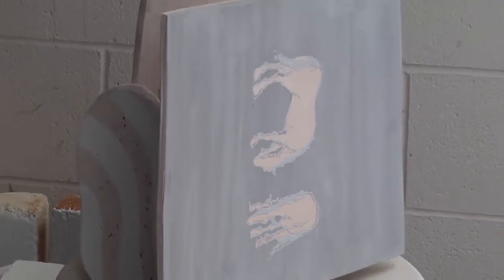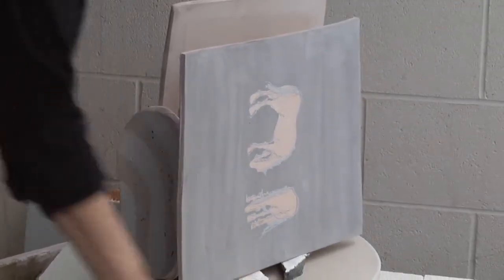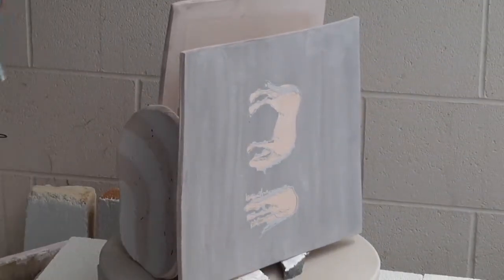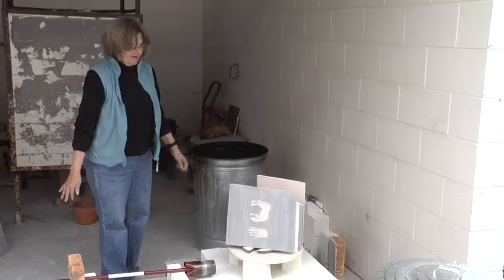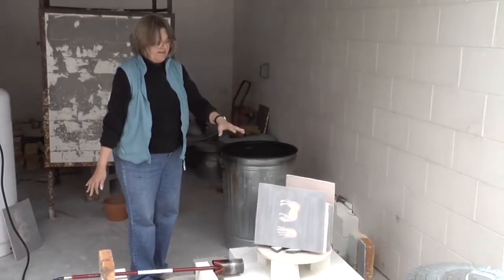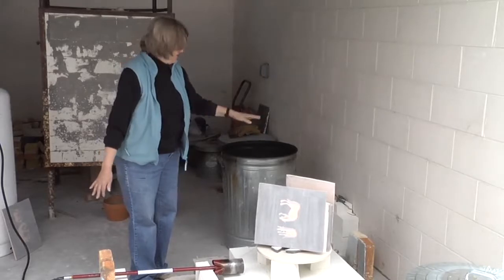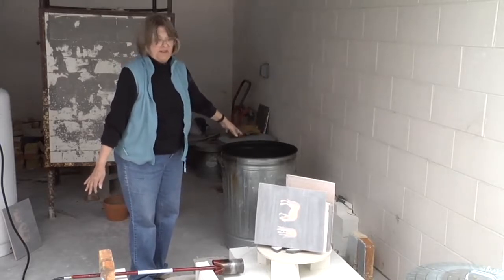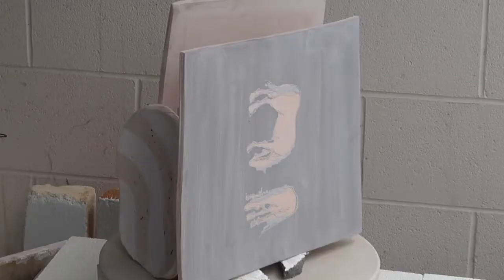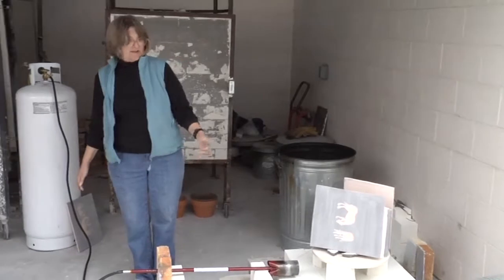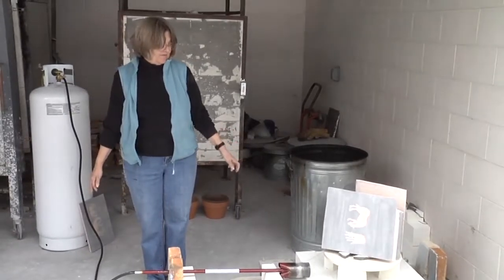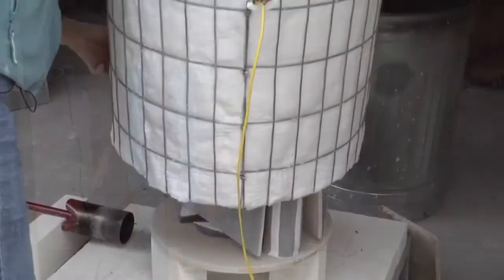And I'm going to turn it on and start it up. And this firing goes to 1850. And then after it hits that temperature, we take the kiln off and put it in a reduction chamber of newspaper and straw or whatever we have around. So that's the process, and it should take about 45 minutes to hit temperature. So we'll start out slow and turn it up every few minutes, about every 5 minutes.